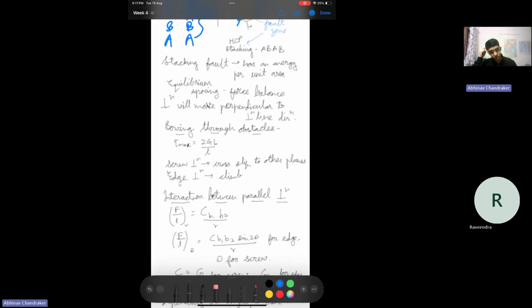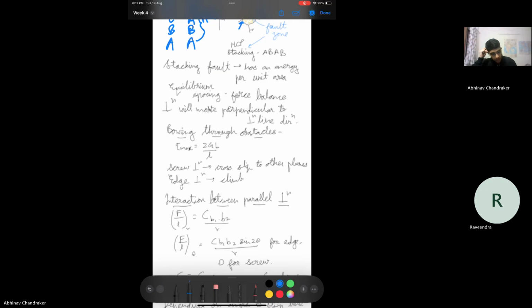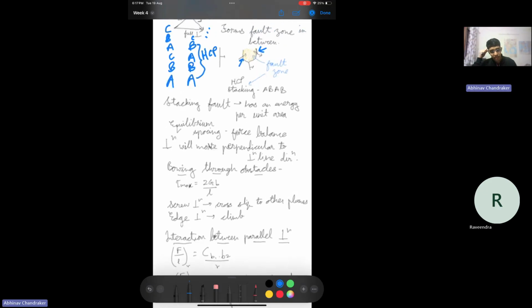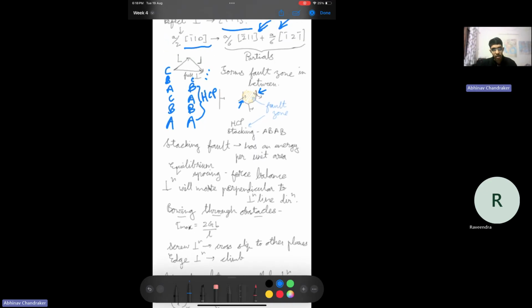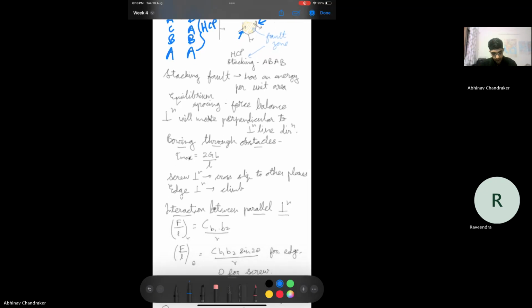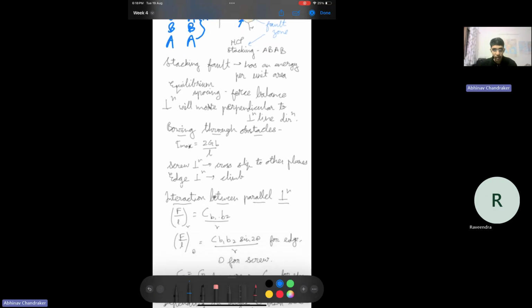There will be an energy associated with this also, which is called the stacking fault energy. When the partial dislocations are at equilibrium, there will be a balance of forces. Since there's some energy associated with formation of the fault, or some surface tension associated, the system will try to reduce that by bringing the partials together and constricting such that the partials will again form a full dislocation. So that will be the attractive force. But there will also be a repulsive force because the partials have different Burgers vectors. So due to the stress field between the two partials, there will be a repulsion between them. So that was about partial dislocations.